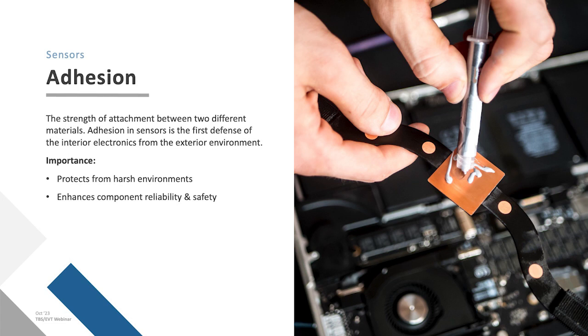This exposure makes sensors much more vulnerable to moisture, high vibration, and impact potential, making adhesion critical to longevity. The adhesion of a potting compound in a sensor is the first line of protection from the exterior environment. A failure in adhesion can cause a direct leak path, resulting in sensor failure. Specifically, adhesion refers to the strength of attachment between two different materials.